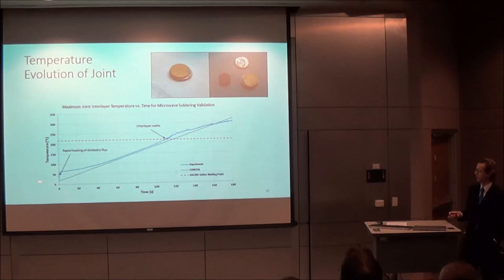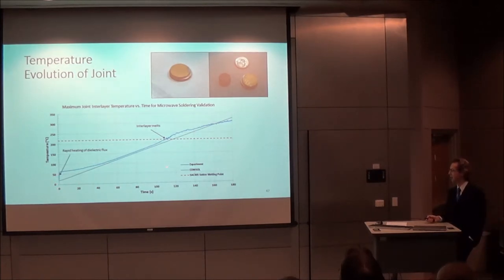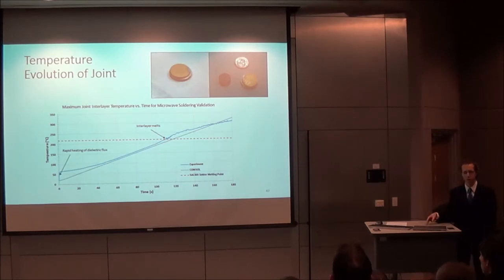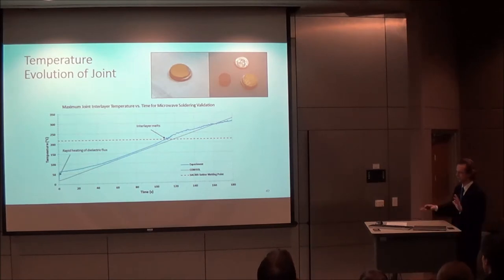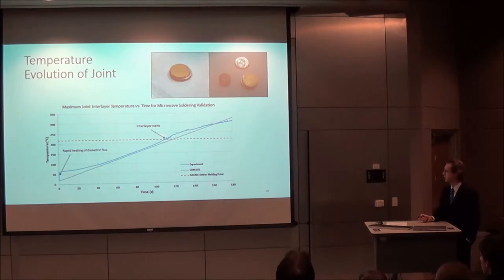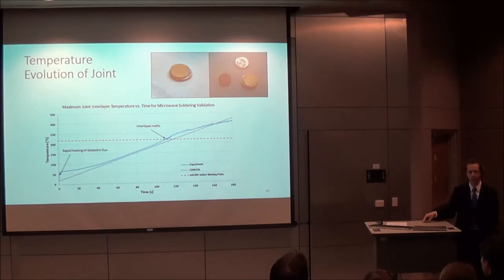This graph shows the temperature evolution of the interlayer over the whole time of the experiment, as well as the prediction by COMSOL. Some things to point out: there's a rapid heating of the dielectric flux at the beginning because it contained polar molecular compounds such as zinc chloride, which heated rapidly and then dissipated. But overall, most of the heat was generated from the ferrite and transferred to the joint. The orange dashed line represents the melting point of the solder used. Where that intersects, a phase change occurs and the solder starts to melt and heat in different places, so the temperature response changes accordingly. The final prediction was within 5% of the actual result in terms of the overall temperature increase. So the numerical prediction represented fairly well what actually happened in the experiment.